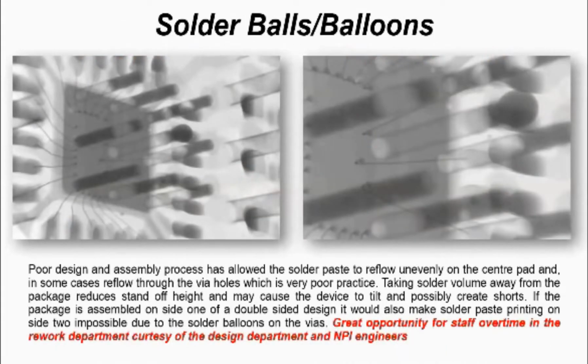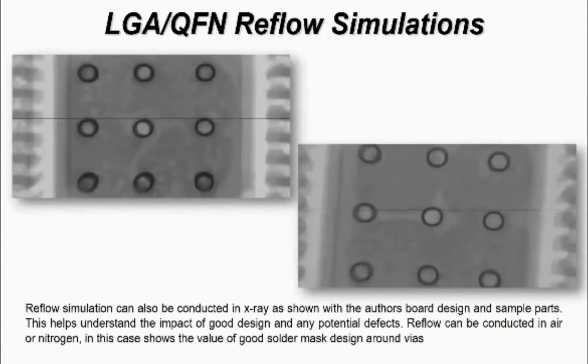Back to the vias for a second. Again, an old photograph of mine, and what you can see here is the loss of solder volume to the vias. Now, if solder wets beautifully, wonderfully, it actually pulls the package down to the surface of the board. So consequently, that displaces solder even more, and possibly could in fact cause solder shorts around the outside termination of the part. So anything that stops you changing your process, i.e. losing volume of material you've actually put there for a purpose, has got to be an advantage.